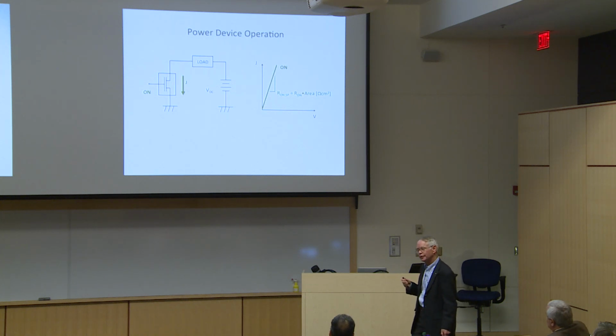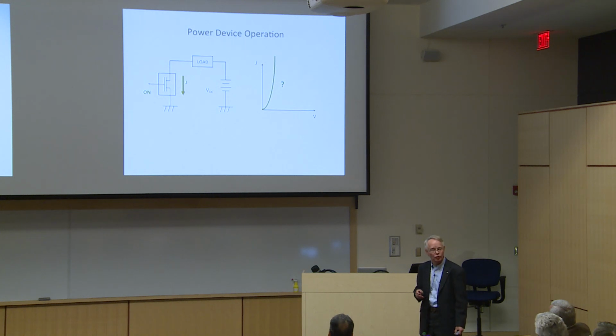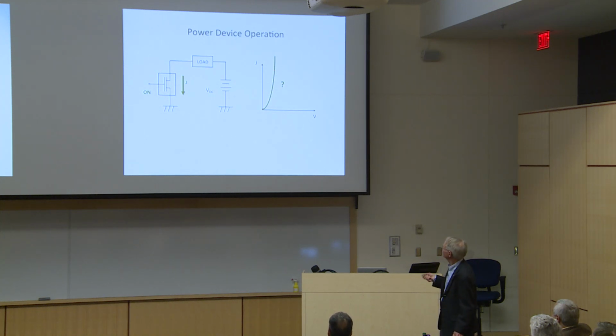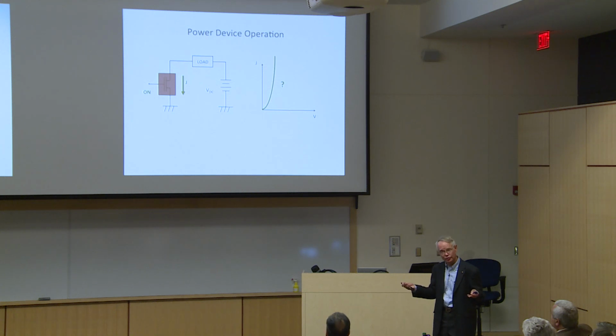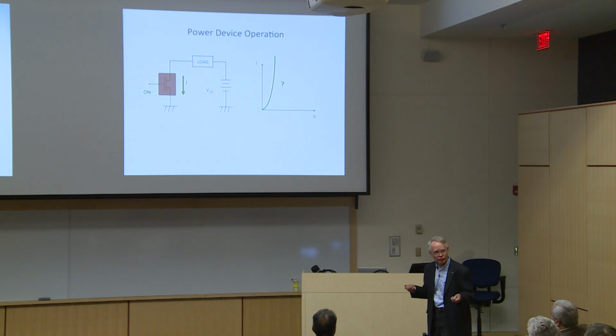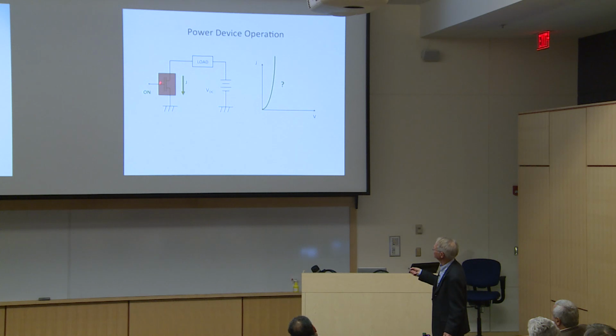If I was comparing it to an IGBT or a Thyristor, they're not linear. They're more like diodes. They have an offset voltage. And I can't define a resistance here. The resistance is the slope of the line, and it's changing. So the better way to compare devices is to look at the power dissipation. If I look at the device here when it's in the on state, it gets hot. And there's a maximum temperature you can allow, and the package will only dissipate so many watts per square centimeter with that temperature drop. Typically about 300 watts per square centimeter for really good packages. So you have to operate the device so that it dissipates less than 300 watts per centimeter squared.